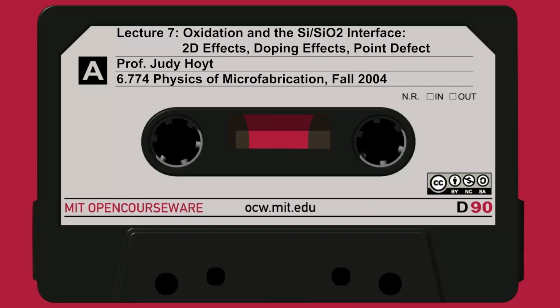And then you can strip the oxide at the end if you want and make electrical measurements, which turns out not to be so easy to contact a pillar that's only 20 angstroms, a little minor technical problem, but he was able to do it. And in fact, this is a cross-section TEM, a transmission electron micrograph, of one of Harvey's pillars. What you can see here is 2 nanometers in diameter, so it's 20 angstroms. So it's a really tiny wire of silicon. And this amorphous-looking material all the way around it on the sides is the silicon dioxide that he grew.